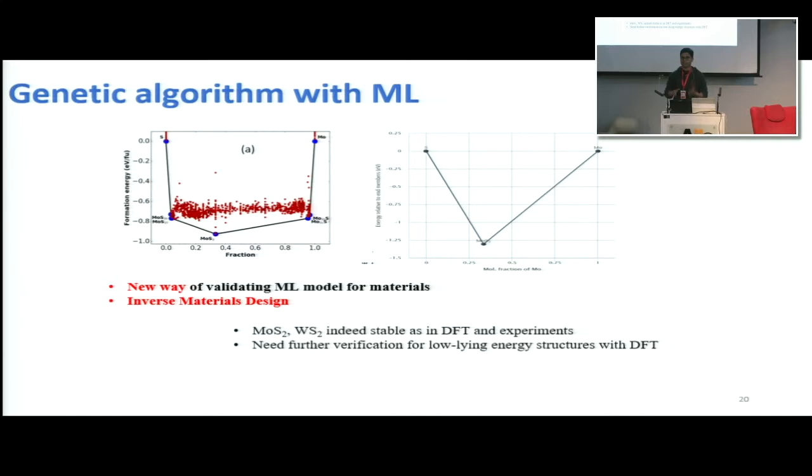What we found very surprisingly and interestingly is that the MoS2 H structure, which in reality is the most stable phase of MoS2, was actually stable in the machine learning model too. In conventional DFT or classical potentials, there is a governing Hamiltonian, which helps you constrain the space of materials. But in the data-driven approach there was no such constraint, and still it was able to find MoS2 on the convex hull, which is very promising to me.